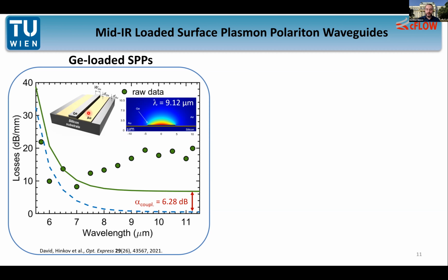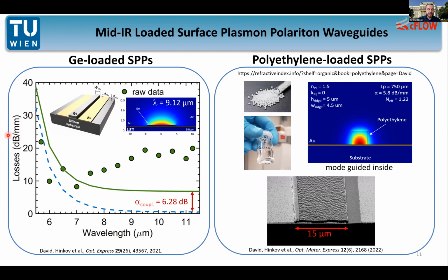Then there is a second type of waveguide that we can use, basically also a plasmonic waveguide. By just substituting the germanium on top with another material, with a polymer like polyethylene, for example, we can go from a semiconductor loaded to a dielectric loaded waveguide. And here, polyethylene is this crystalline material. We can dissolve it into a solution using, for example, toluene. And then we developed in our lab a spin coating process,